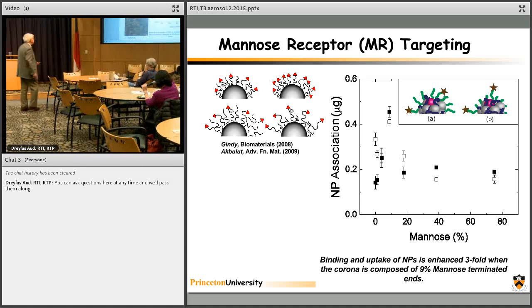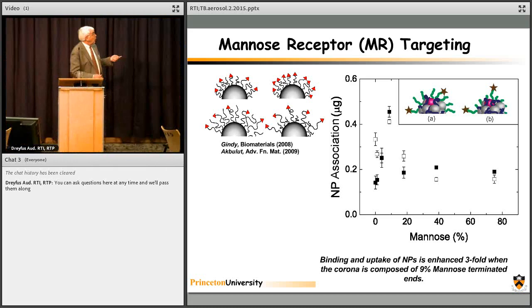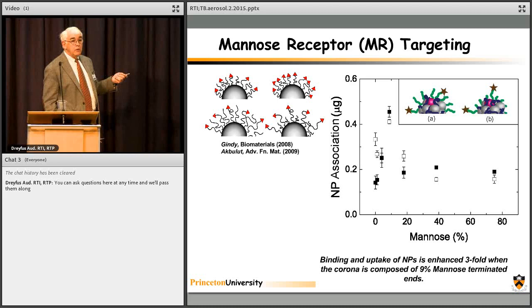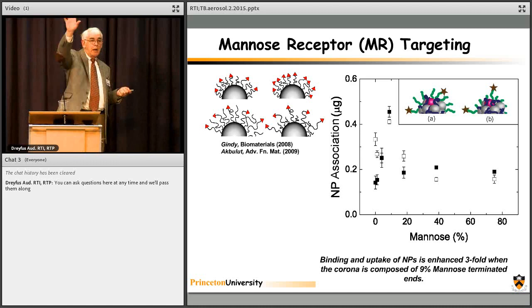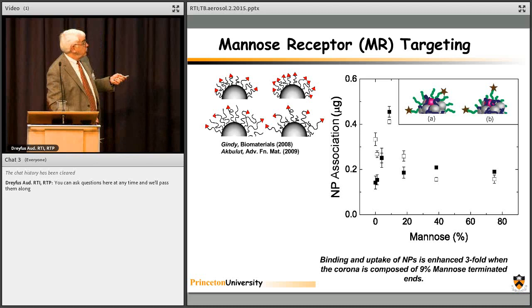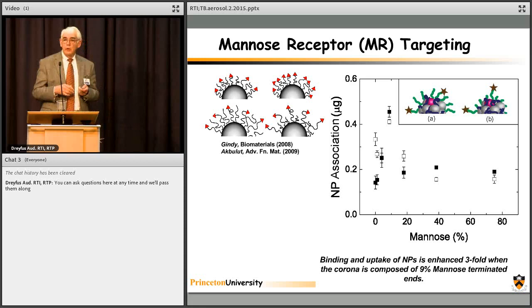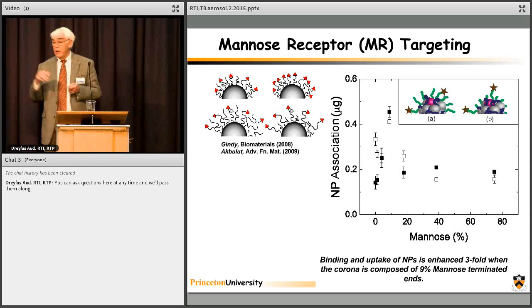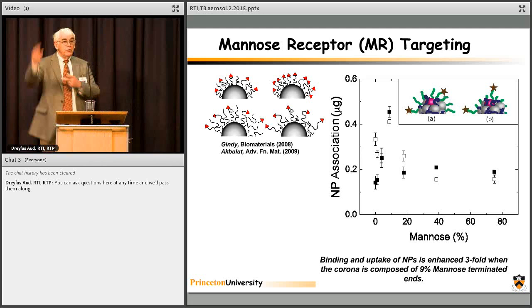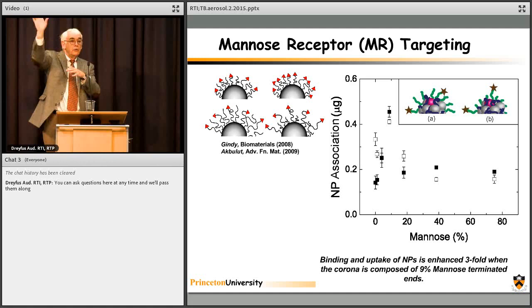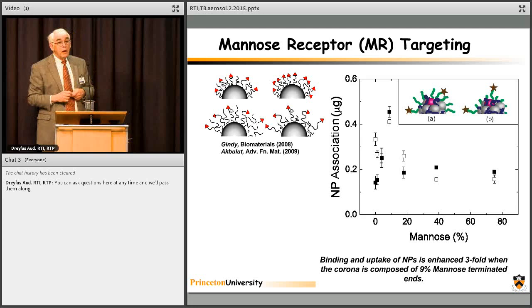So I didn't say that the white dots are 2K steric stabilizing and 5K mannose targeting chain. So that's a longer chain that could potentially reach out past the steric protecting layer. What you find is that at 0% mannose, that is just the 2K, you get much more uptake. So the 2K layer is not protective enough against protein adsorption, so that's not good. And that's sort of known in the liposome world, too, that people know you get on 2K and you're not getting as much stealth protection as you do at 5K. But the maximum here is pretty much the same. Our hypothesis was that if it stuck out further, it wouldn't be interfered with by all the other PEG chains. It's not folded down as frequently, and so the uptake might be better. But it really doesn't make much difference. So now we haven't done the experiment of 2K stealth layer plus mannose on a